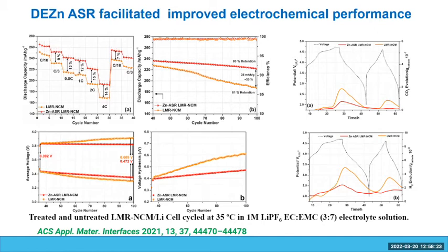One more thing, here, even if we go to 4C, it is not a great surprise, but the zinc oxide should be a better lithium-ion conductive material from two different aspects. One is that the lithium zincate itself is a better conductor, and the second is that these are grains, and there is also more surface conductivity of the lithium ion. But when we are going to 4C here, we have 14% improvement by the coating of the zincate.